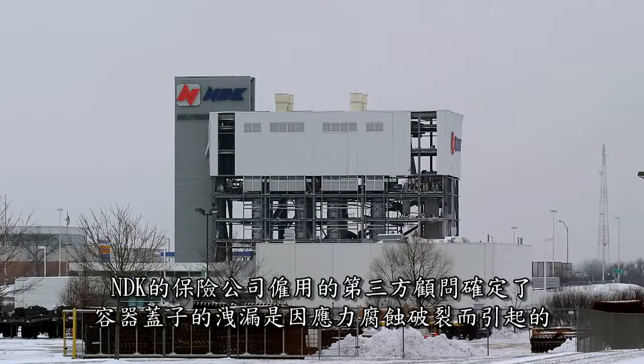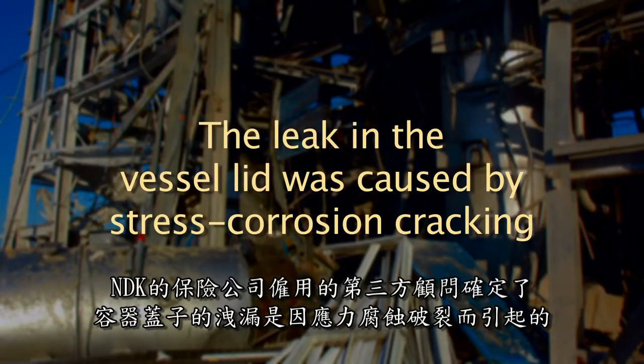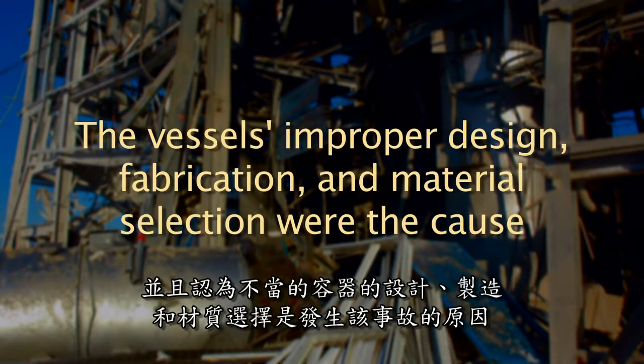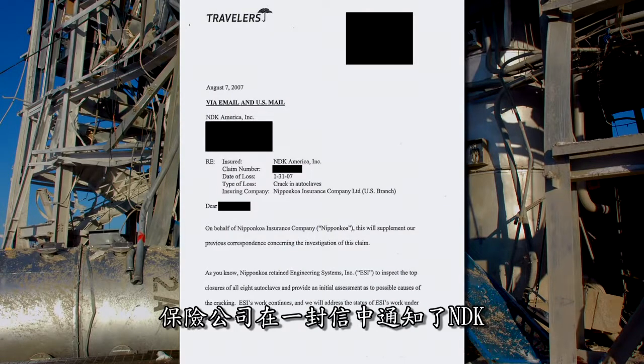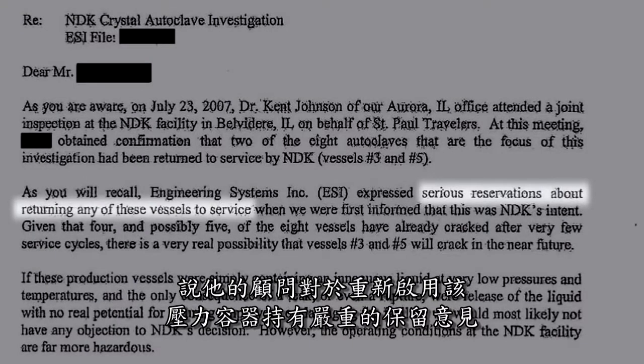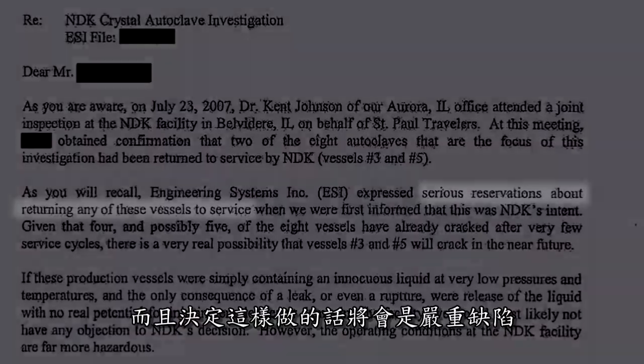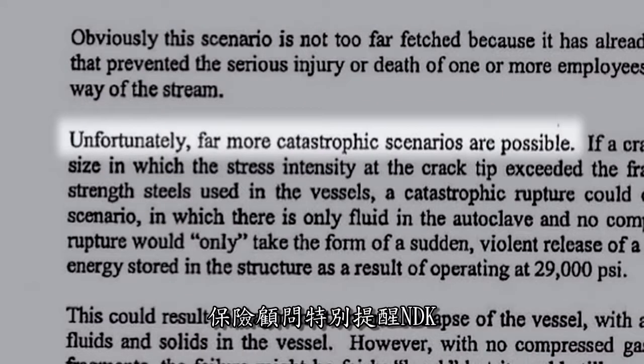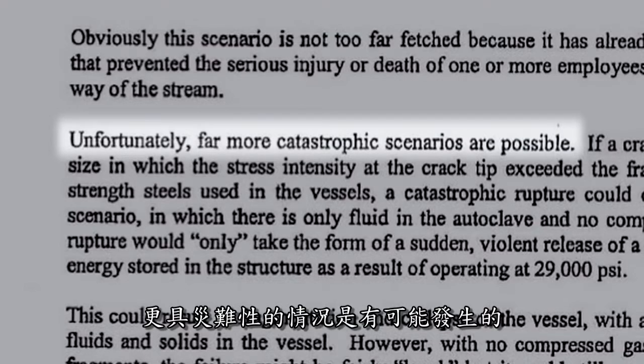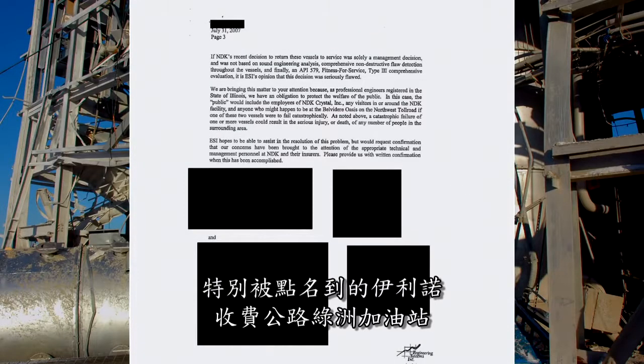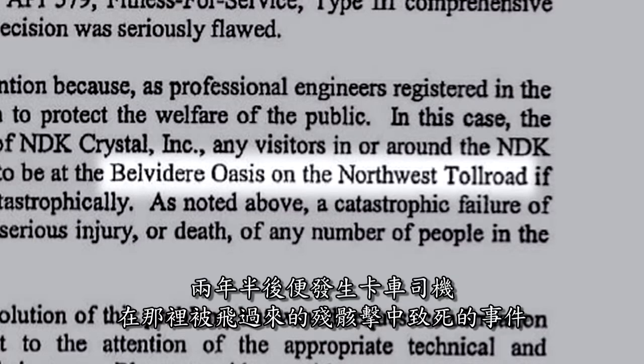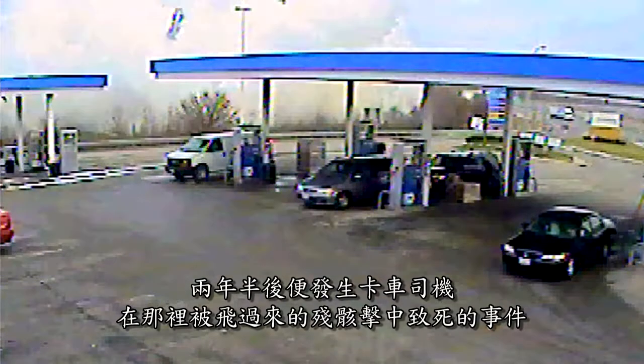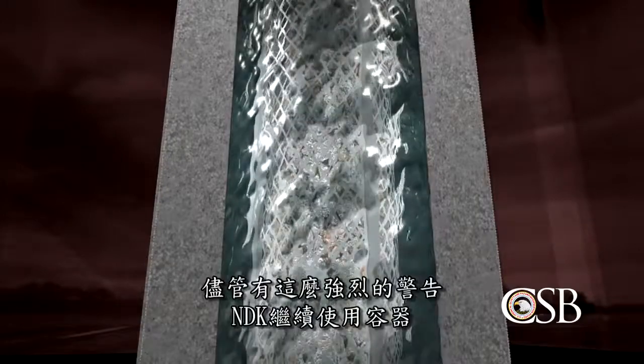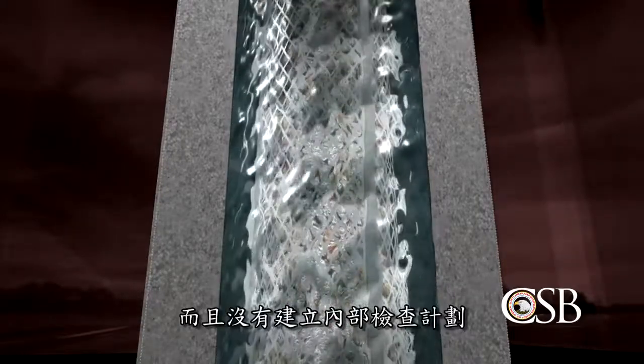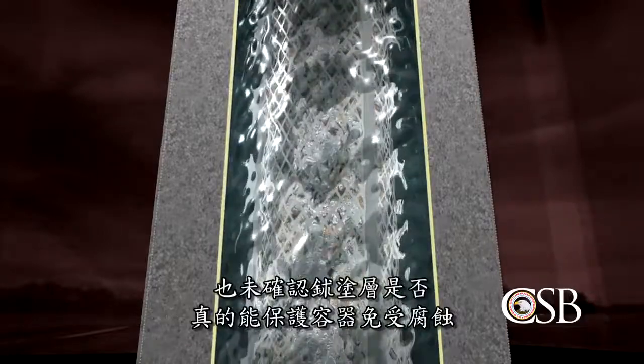A third-party consultant, hired by NDK's insurance company, determined that the leak in the vessel lid was caused by stress corrosion cracking and concluded that the vessel's improper design, fabrication, and material selection were the cause. Later, in August of 2007, the insurance company informed NDK in a letter that its consultant had serious reservations about returning the pressure vessels to service, and that a decision to do so would be seriously flawed. The insurance consultant specifically cautioned NDK that far more catastrophic scenarios are possible, putting NDK employees and the public at risk, specifically naming the Illinois Tollway Oasis gas station where the truck driver would be killed by flying debris 2.5 years later. Despite this strong warning, NDK continued to operate the vessels without establishing an internal inspection program or verifying whether the Alonized coating was in fact protecting the vessels from corrosion.